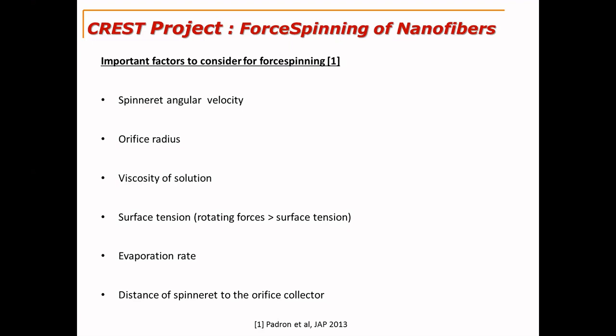Viscosity of the solution also plays a very important role. If the solution is too viscous, the viscous forces will dominate the centrifugal force and the solution will not flow freely inside the spinneret, and it will not come out through the needle and generate the fibers. So the viscosity of the solution should be within a range such that it compensates the centrifugal force, and the centrifugal force can generate the nanofibers.